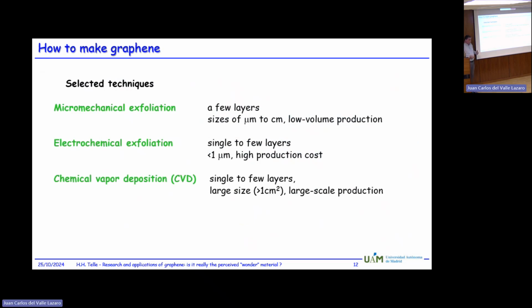So how do you actually make graphene? Because on the previous slide, we saw you take 1 layer of graphite, but that is easier said than done, at least on paper. So there are 3 main techniques, there are many others as well, which are applied these days for commercial graphene samples. One is micromechanical exfoliation. And that is actually how I produced my first graphene samples. Take a piece of graphite, a little bit of sellotape on top, pull the sellotape off, and you have graphene on the surface of the sellotape. This is possible, but for a mass market, this is not a very good solution because it's very time-consuming. You can do it only in small quantities.